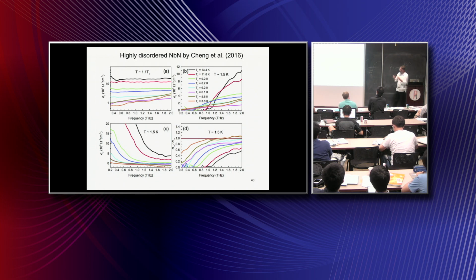There's a bunch of details with this, but what I want to point out is this is the optical conductivity as a function of frequency, and you can see there's a distinct threshold here. As we make the system higher and higher disorder, let's say this is lowish disorder and this is higher disorder, the disorder is getting larger and larger. As the disorder gets larger, the conductivity is getting smaller, and at the same time Tc is getting smaller. This threshold goes down. And then there starts to be very non-trivial behavior right near the localization transition, but that's a different story, or let's say a more extended talk.